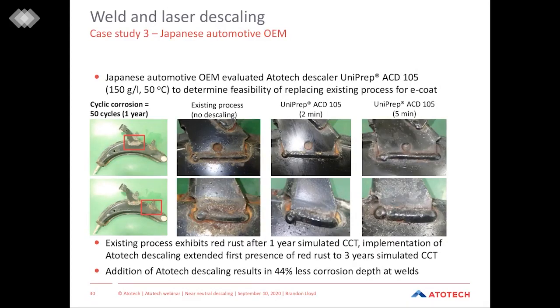The last case study is with a Japanese automotive OEM. This OEM evaluated Atotech's descalers, being Uniprep ACD 105 at 150 grams per liter and 50 degrees C, to determine the feasibility of replacing the existing process for E-coat applications. Their evaluation method was cyclic corrosion, and 50 cycles is equal to 1 year of exposure for them.